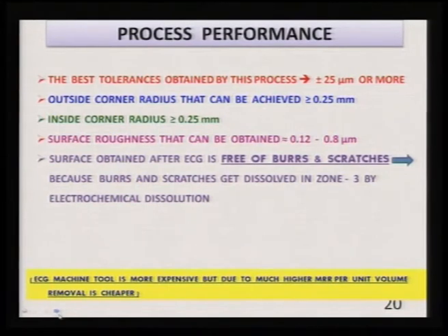The surface obtained after electrochemical grinding is free of burrs and scratches, which I have already explained in the earlier slide, because burrs and scratches get dissolved in zone 3 of the electrochemical grinding process by electrochemical dissolution.